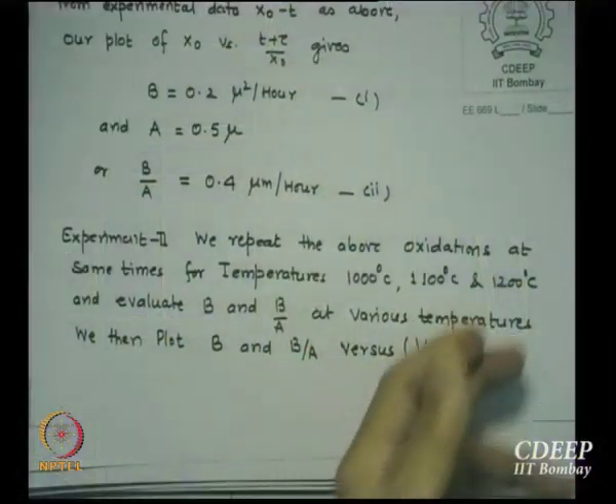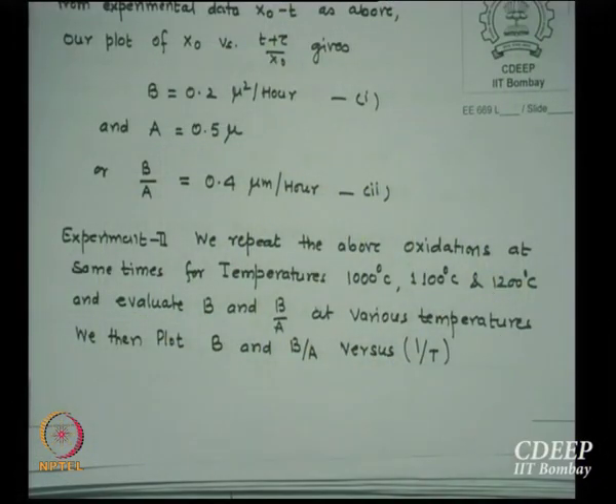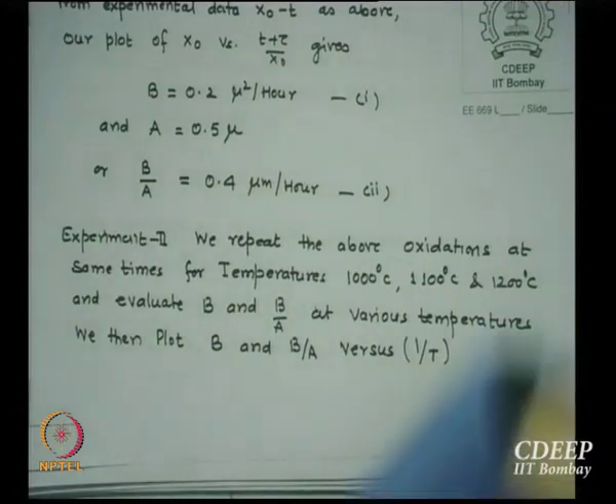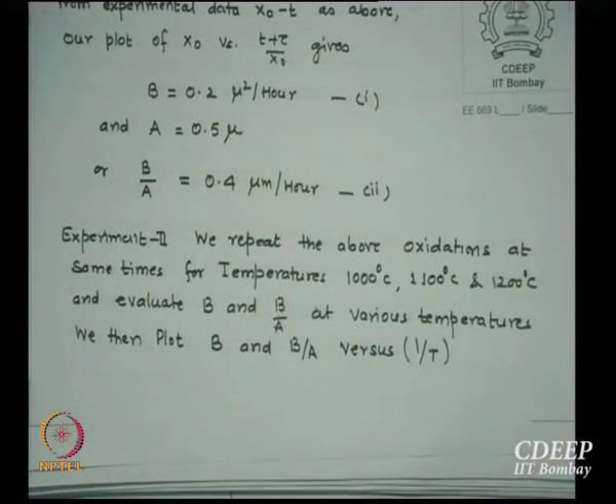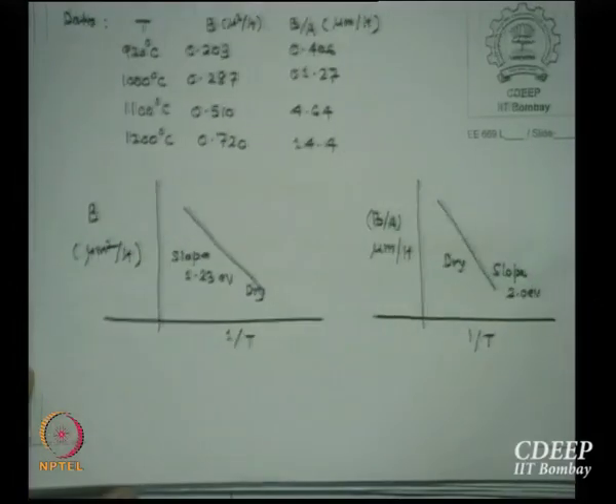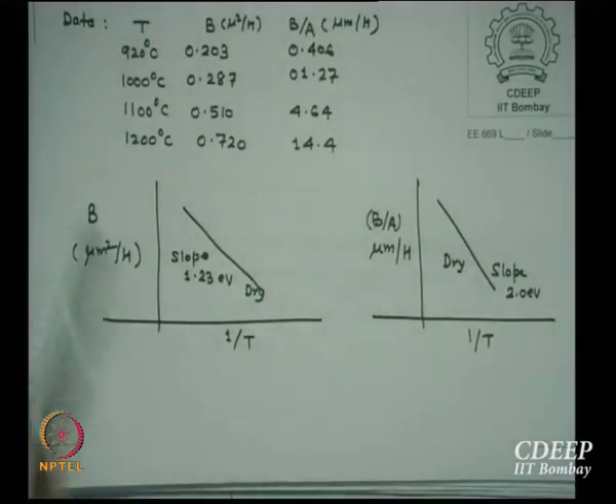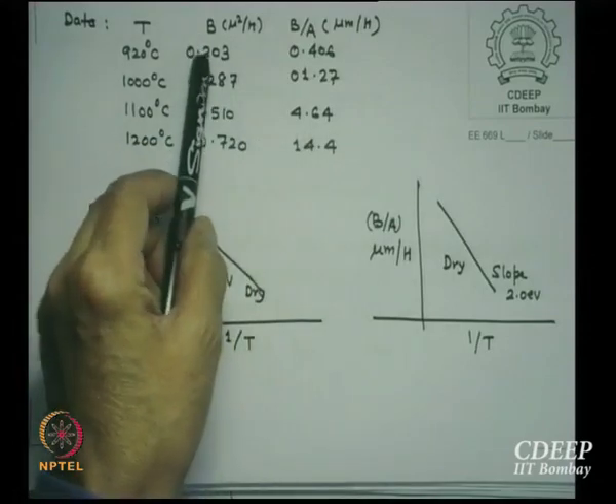So we actually do repeated experiments at 1000, 1100 and 1200. Monitor oxide thicknesses at the same times, replot x0 versus time, and get B and A for all of them, for different temperatures. This is for 920, repeat it for 1000, repeat it for 1100, repeat it for 1200. If I do this, the data I get is 920 is this and 1200 is this. This is B by A. Please remember units. B is expressed as micron square per hour and B by A is expressed as micron per hour. Linear and parabolic rate constants.